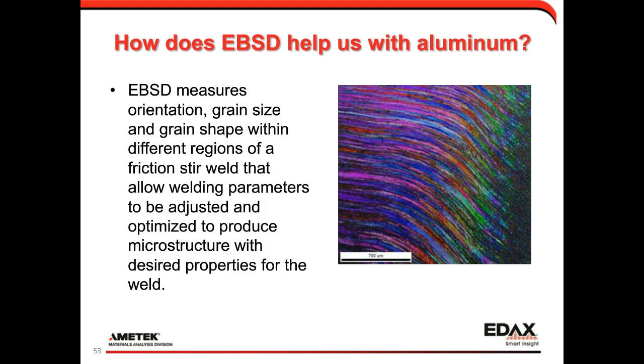So this is just a quick summary for aluminum. How does EBSD help us with aluminum characterization? We can measure the orientation, grain size, and shape within different regions of a friction stir weld. That would allow us to adjust the welding parameters to produce an optimized microstructure with the properties you want from the weld.